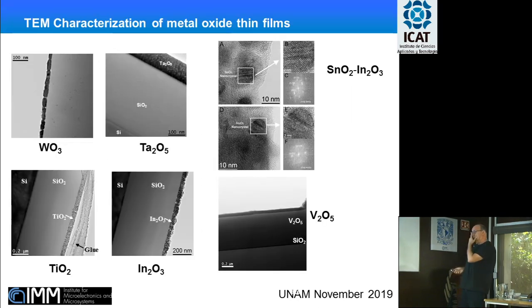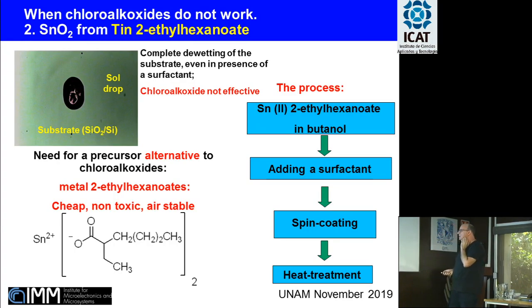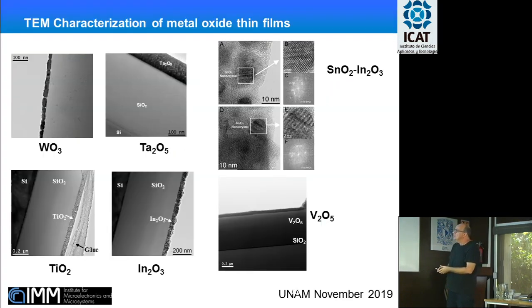Some examples. The process indeed proved to be extremely successful for making, for instance, tungsten oxide, tantalum oxide, indium oxide, vanadium oxide, and so on. This is a panoramic view of some spin-coated films, made also by other processes that we will see in the following. But you can see that in general the films are extremely uniform. They cover the whole substrate, and they could be processed, as we shall see at the end, by microelectronic procedures to prepare the final sensing devices.